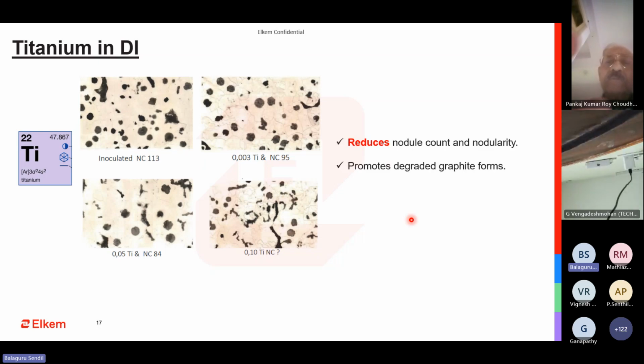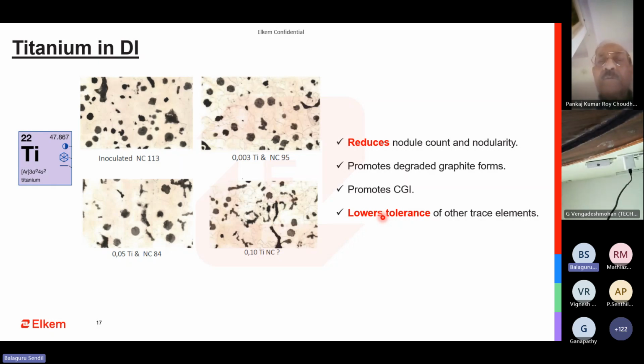It reduces nodule count and nodularity, and not only reduces it, it promotes degenerated graphite, it promotes CGI. The most major problem is that when you have titanium, it lowers the tolerances of other trace elements. So the liquid metal can basically tolerate a certain amount of lead, arsenic, antimony, bismuth, all these things. But once your titanium is there, the amount of tolerance your liquid metal inherently has will come down.